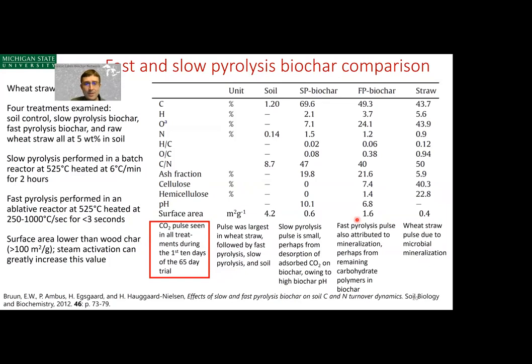Well, this difference in properties has some ramifications. This experiment observed that there was a CO2 pulse from the different soils collected during the first 10 days of a 65-day trial. The pulse was found to be greatest if you just land applied the wheat straw. The wheat straw was very accessible, very labile to the microorganisms in the soil, and so you've got a large CO2 pulse as a result.